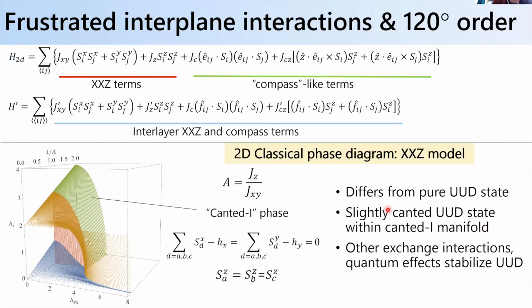our powder data is not sensitive enough to really resolve a subtle canting within the up-up-down state. Or it could be that other exchange interactions or quantum effects act to stabilize it a bit more, because this is just the classical phase diagram. But nevertheless, this is the phase diagram they mapped out, and it supports the experimental observation with this caveat, with the slight canting that should occur.